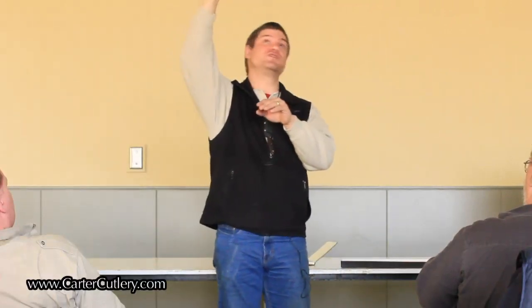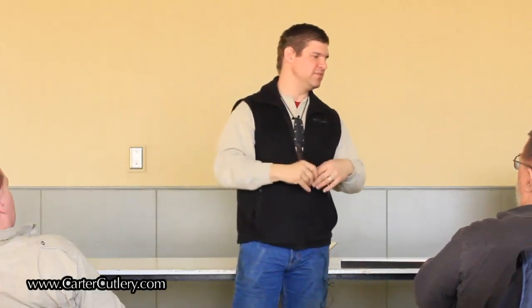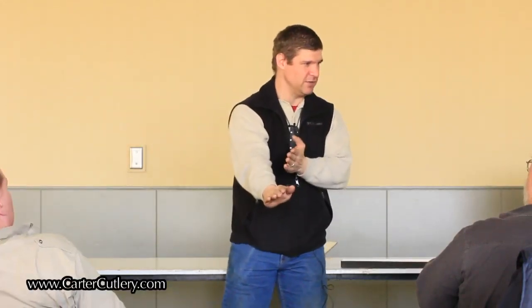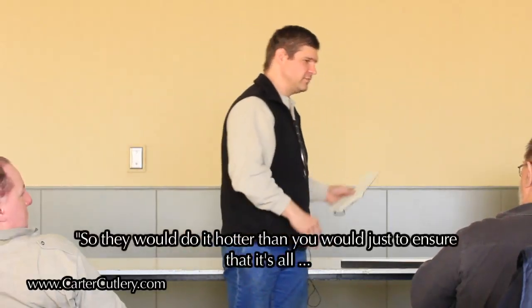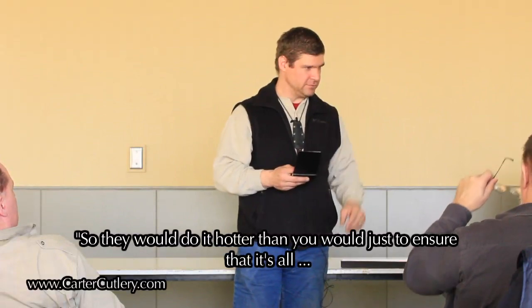To the point where you've tried to forge weld at such a high temperature that the steel cracks and sparkles, and you burned it up like burning an apple pie in an oven at 500 degrees for 10 hours. I mean, you ruined it. But we're looking for perfectly forge welded, but only 5 degrees above the temperature where we've seen faint lines. Does that make sense? So the Japanese bladesmith is trying to hit it right on that threshold every time, whereas Western style cutlery is like, no, I want an extra element of safety. Give me safety. Make sure that these things are going to be marketable. So they would do it hotter than you would, just to ensure that it's all...